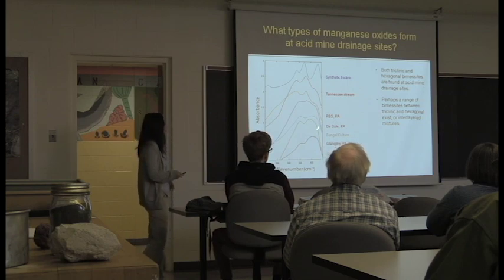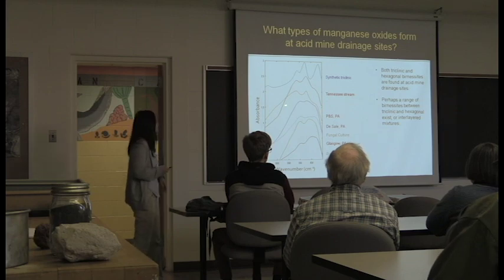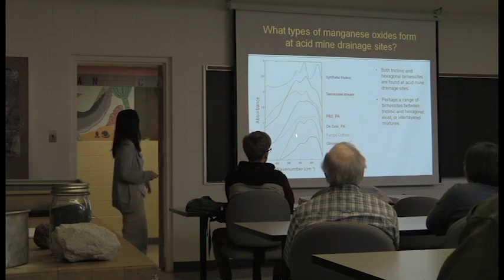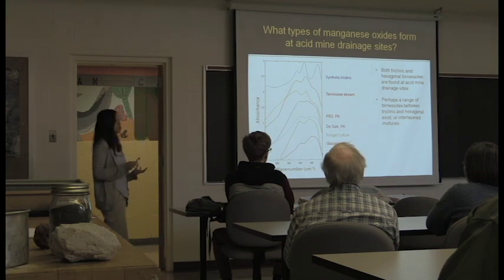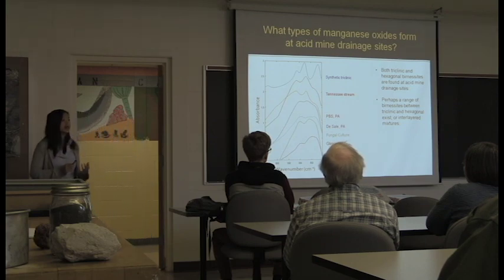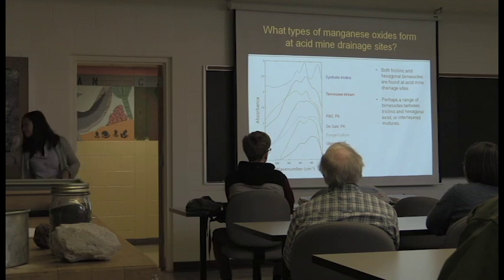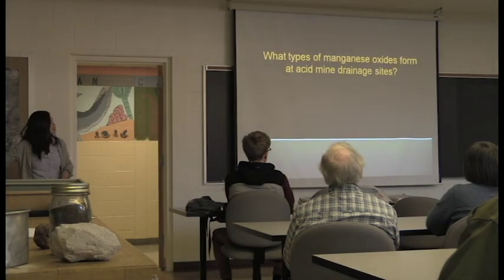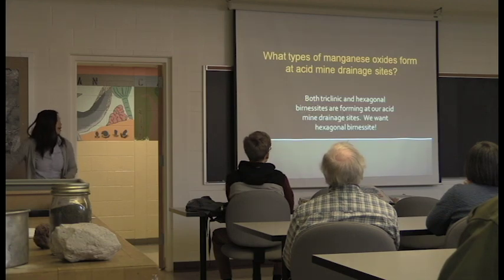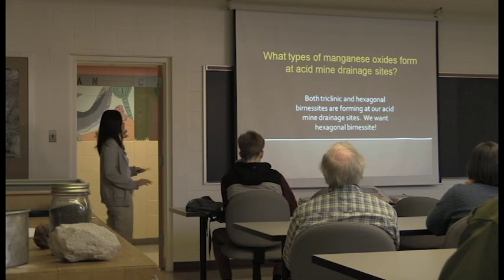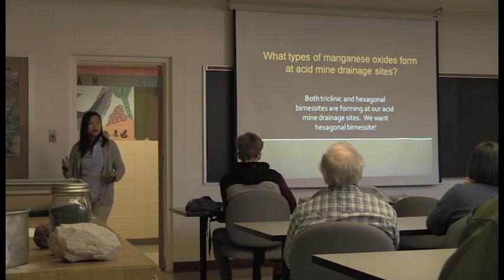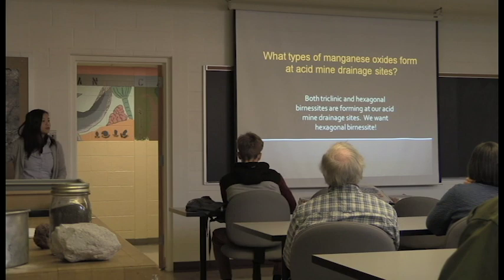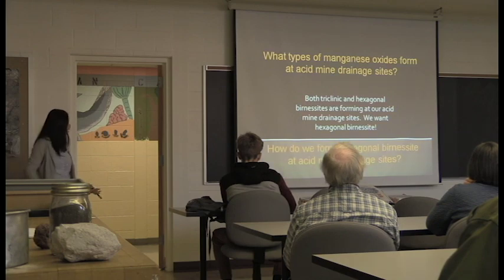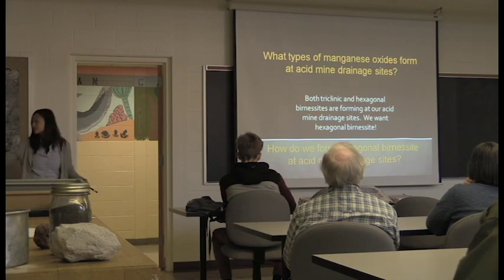And so we're finding there's some triclinic and there's some hexagonal across these different acid mine drainage sites. If we look at all of these in the order that I've put them in, you might even see that there's some gradual peak shift from the top to the bottom, and that some of these might even be something in between, or a mixture between triclinic and hexagonal birnessite. So we asked the question, what types of manganese oxides form at these acid mine drainage sites? We're finding that both triclinic and hexagonal birnessites are forming, but we want hexagonal birnessite, right, because it has more holes. So how do we form hexagonal birnessite at these acid mine drainage sites?